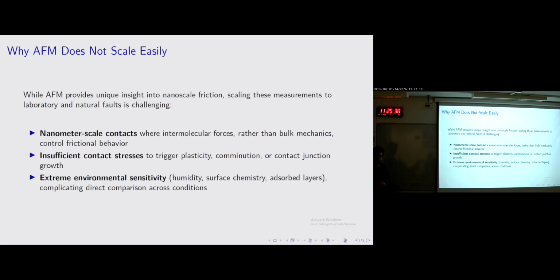Second, the contact stresses from these tests are really, really small. There's no plastic deformation, so obviously there's no contact area growth in these experiments. And lastly, these types of tests are really, really sensitive to the environmental conditions, changes in humidity, temperatures. If the person making the tests had lunch and washed their hands, there's no way that they got all the leftover food from their fingers. I'm talking about really molecular level hydrocarbons from a sandwich. And they touch the sample, that's going to come up in these friction tests at the nanometer scale. They're really, really sensitive to the surface chemistry. So they don't scale easily.